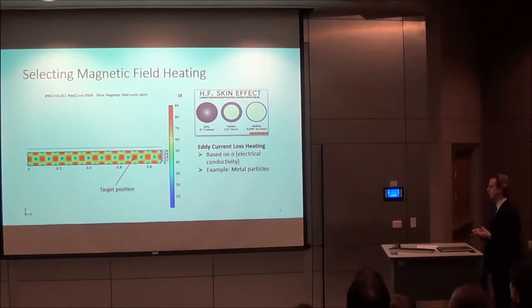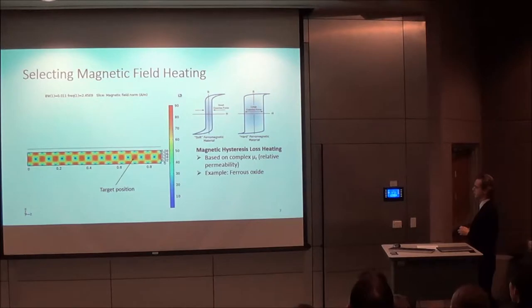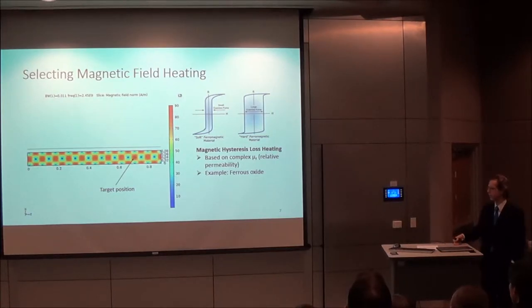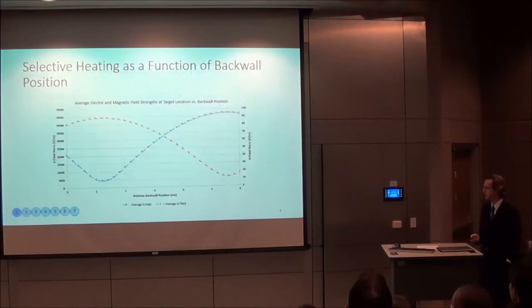substantive. In addition, magnetic materials experience losses through the hysteresis effect, which happens in magnetizable materials when there's a remnant field, and that produces basically a path that can't be returned upon. And so you have this area that's traced out in the hysteresis curve by magnetizing and demagnetizing the rapidly changing field. And that area represents the losses in magnetic materials such as ferrous oxides.